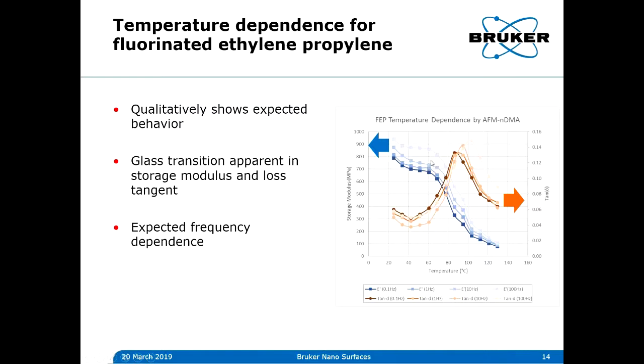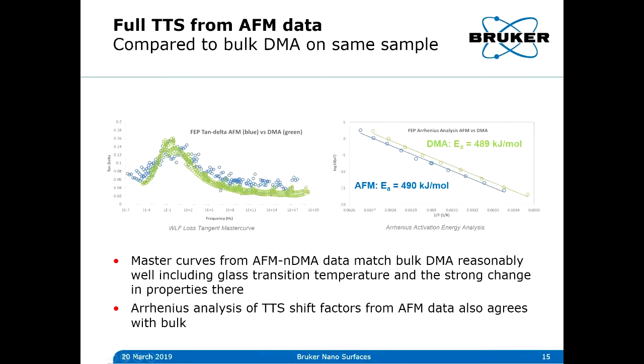And the behavior is pretty much what we expected from Dalia's earlier slide showing what you would expect for storage modulus and loss tangent as a function of temperature. And we're also getting the expected frequency dependence. In other words, the loss tangent is shifting to the right at lower frequencies. So the question is then, how well does this match the bulk measurements? So here we have the bulk measurements in green and the AFM-nDMA measurements in blue. And we get a reasonably good match of both the glass transition temperature and the behavior around the glass transition.